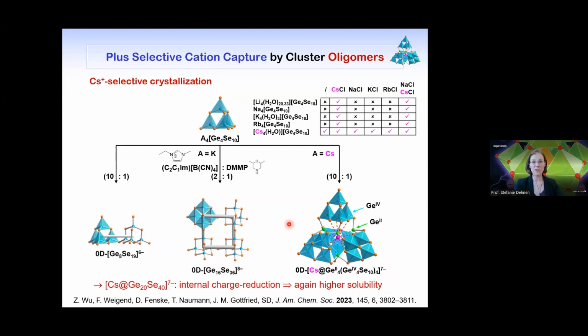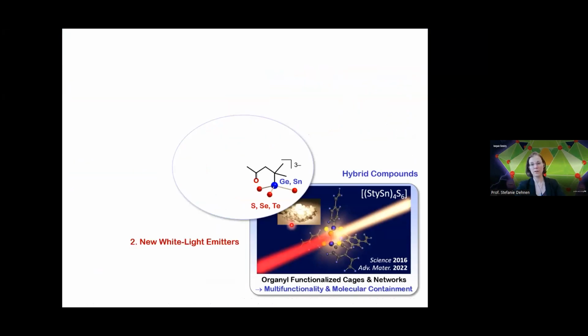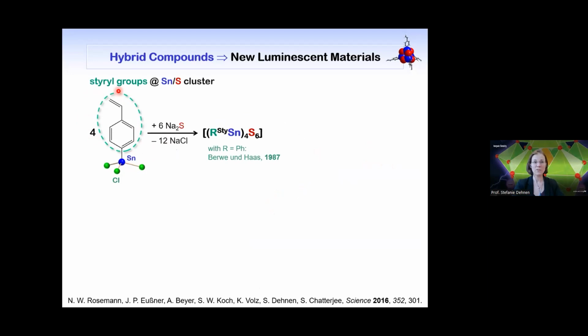So with this, I'd like to switch gears for a very brief story on compounds where the alkyl groups that I've recently briefly talked about are installed from the very beginning. So we don't do that post-synthetically, but use it in the starting material, and this way systematically produce hybrid compounds. Here is a little story about that. We were interested in installing styryl groups on clusters, so we used a styryl tin trichloride, added a sulfide source, and formed this kind of a cluster with 4 styryl tin groups and 6 sulfur atoms. This has been reported with phenyl groups many years back, but we wanted to have the styryl groups for having this functional part here for doing epoxidations or polymerizations or attachment to semiconductor surfaces.